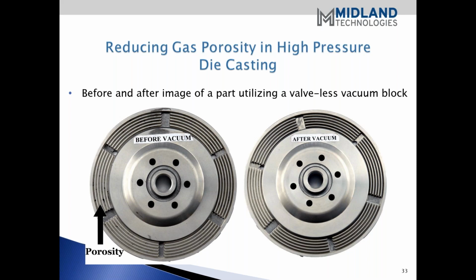This is two illustrations of castings that are heavily machined, and the grooves in both of these castings are essentially as cast. We don't have a picture of the as-cast, but this particular part, as you can see, has a series of grooves machined into it, rather deep. And this particular customer was experiencing higher rates of scrap.